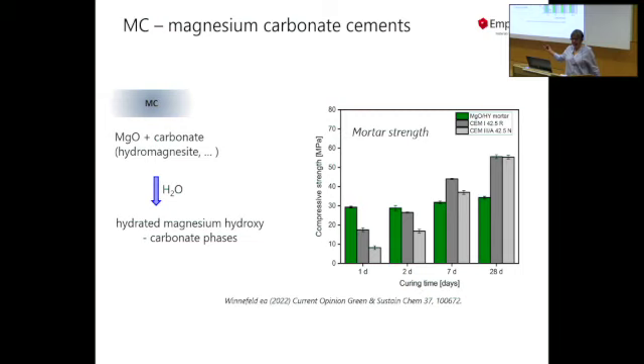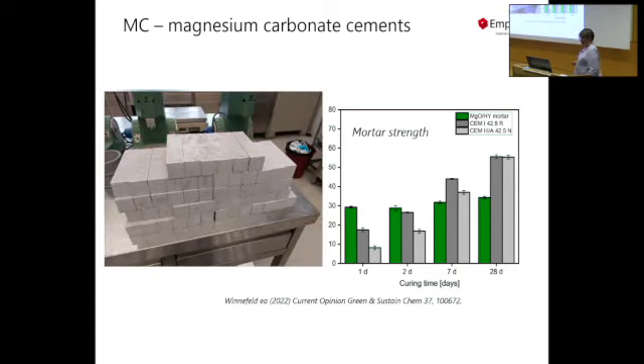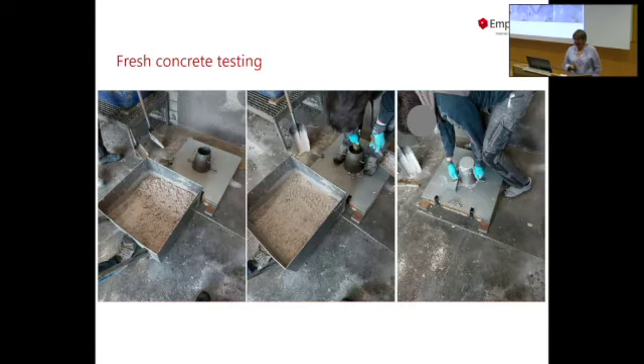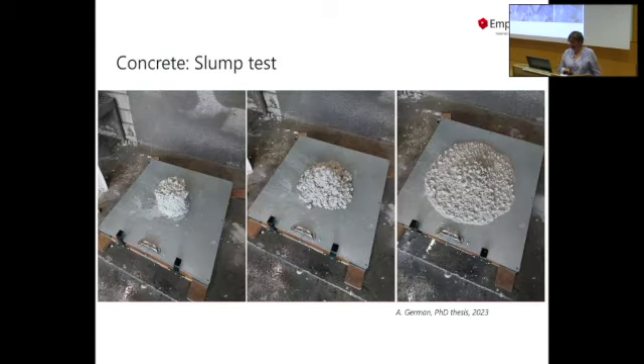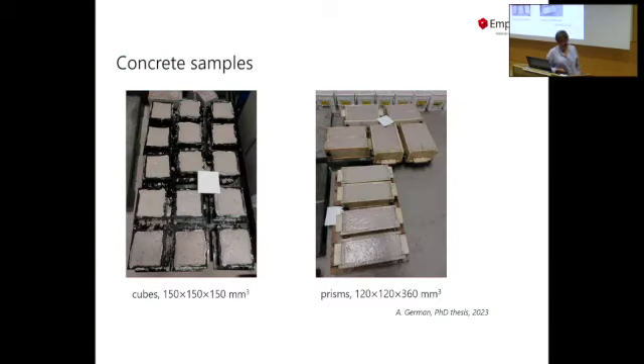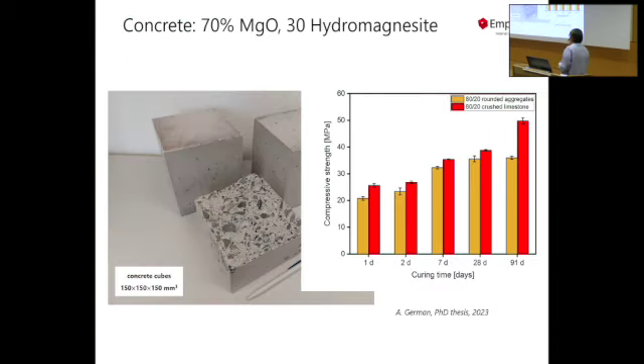For comparison, we have also put a traditional Portland cement in the same test. And actually, even the concrete or the mortars look exactly how normal mortar looks. You also can do fresh concrete testing with it. You can do a slump test. Actually, I didn't note it here, but you have to add a lot of PCEs to get a good slump, but you can solve it, and then you can make all kinds of testing cubes and prisms. And obviously, you also can measure concrete strength.